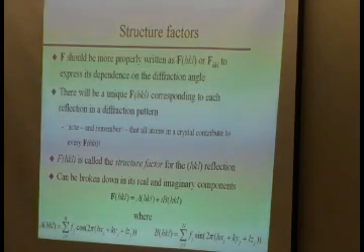And we call it a structure factor. You saw that word somewhere before on one of the handouts where there were Fourier transforms between real and reciprocal space. There was that word structure factor on there, and at that point in time it didn't mean anything to you. This is that structure factor that was on that slide. You should usually write it as F_HKL, whether you put it in parentheses or as a little subscript, because it does depend on the diffraction angle.